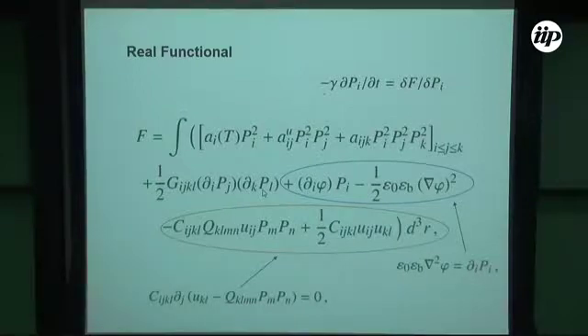And this part of the function would now be enough if we neglect the long-range interactions, but actually we should add here, as I told, the interaction with the electric field and also the elasticity. So what is written in the blue circle is the electrostatic part, and in the yellow circle is the elastic part. So let's now go to the electrostatic part. We have the interaction of the electric field with polarization and the self-energy of the electric field, which is produced by the charges and can also be some external field. Concerning the parameters, epsilon 0 is the electric constant of vacuum, and epsilon b is the so-called background dielectric constant, which is because of the displacement of the nonpolar atoms.